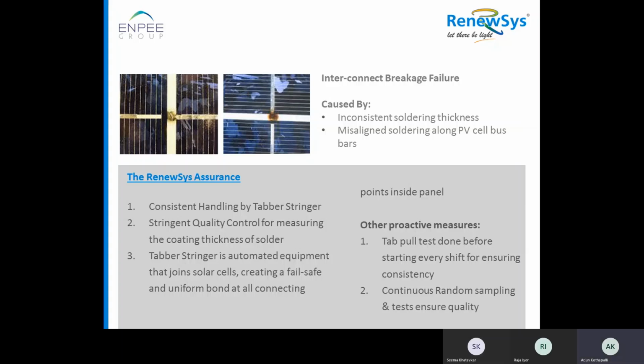RenewSys assures all the cells are soldered with tabber stringers, which are fully automated, and those machines are from Europe. Stringent quality control for measuring the coating thickness of solder wire: yes, we do a solder wire coating thickness check at the incoming stage, that we call IQC, incoming quality control, and randomly we select samples and send them for third-party testing outside the factory to see whether there is any variation in the coating of the solder wire, to ensure that the material quality is maintained consistently. The tabber stringer is fully automated equipment that joins cells.